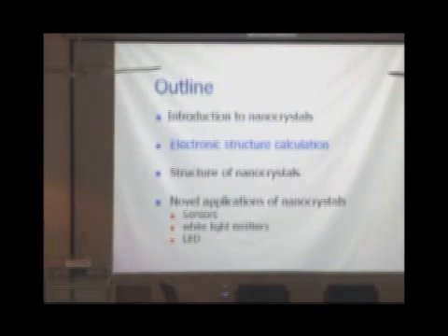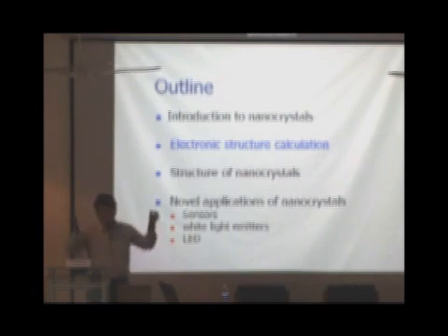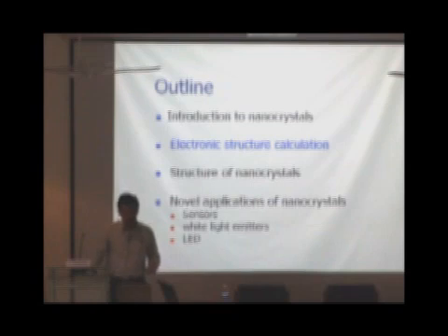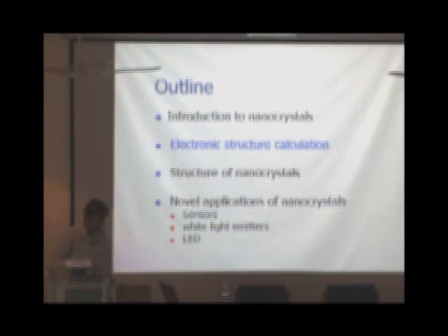Okay, so much for the introduction to the world of semiconductor nanocrystals. I'll move on to electronic structure calculations. I just mentioned briefly that you can use, for example, the particle in a box model, for a spherical particle with infinite walls. If you also agree to use an effective mass instead of the free electron mass, it is known as the effective mass approximation, and was proposed as early as 1982 by Louis Brus, who is considered to be one of the fathers of nanoscience.